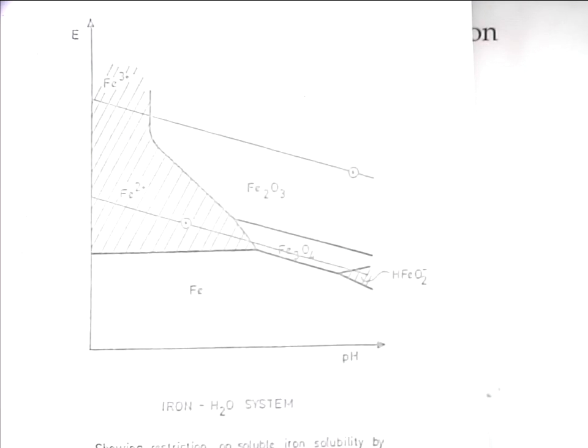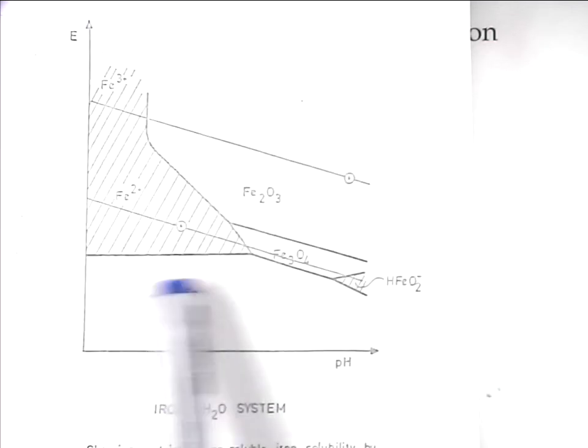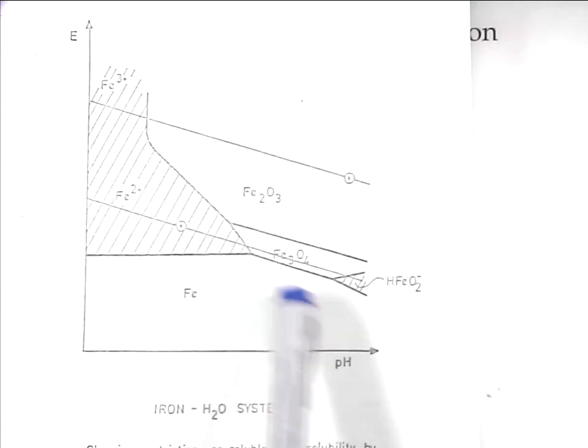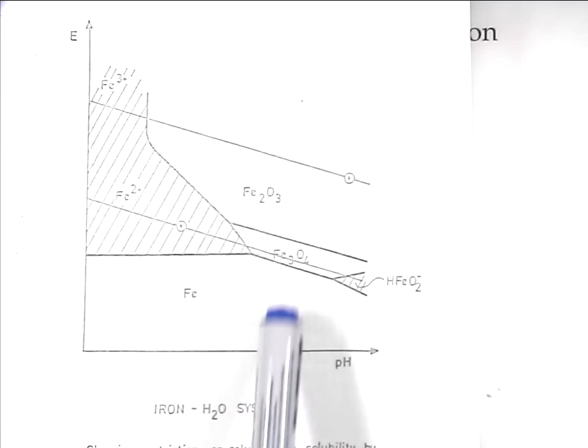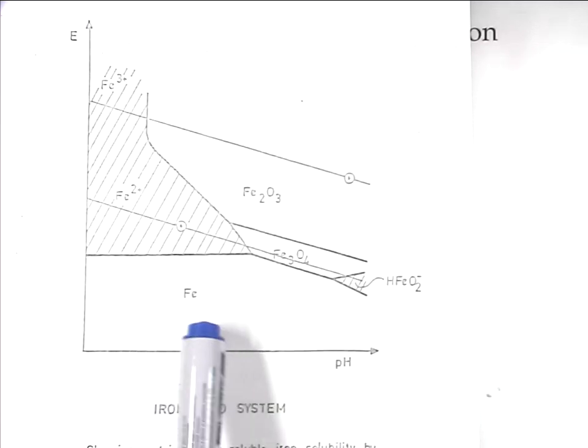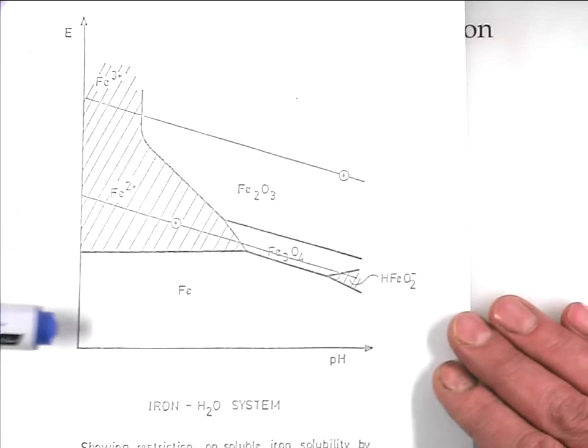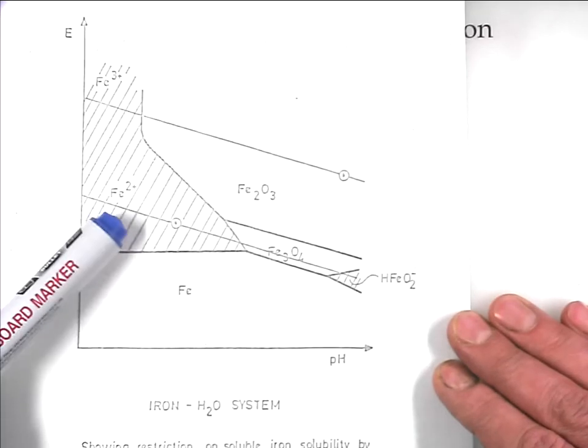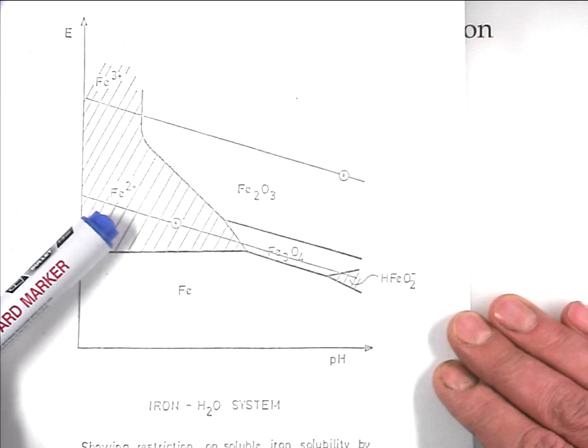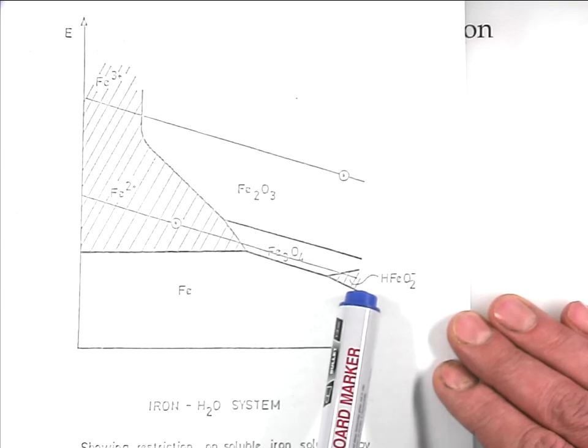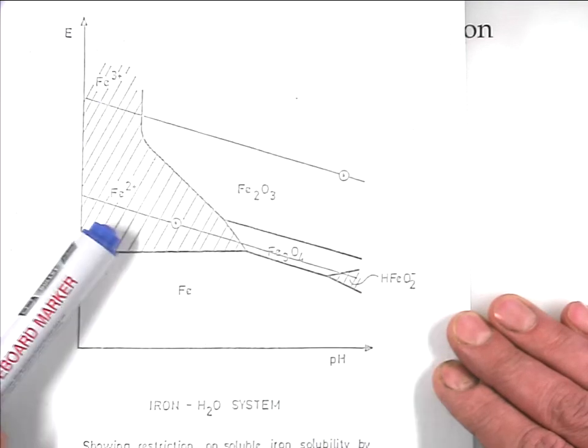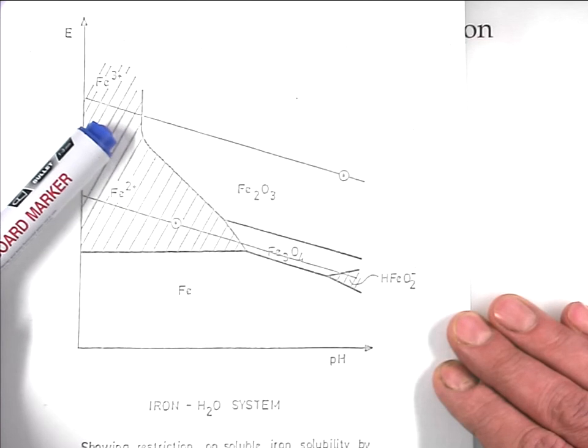Sorry, the passivity. Where this Fe3O4 is, that's a passive layer. So this just starts to corrode, and then it blocks off any further corrosion. Fe2O3 is porous. You can get that at higher potentials, as it indicates, but it's a porous film rather than a passive film. So that's brown rust. It just carries on corroding.